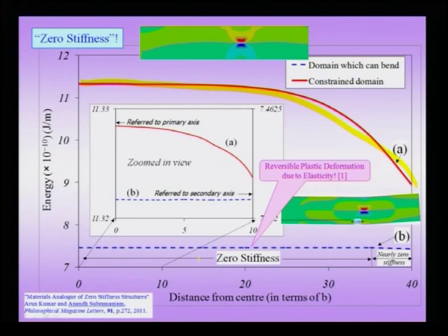Now, if you talk about a dislocation in a thin cylinder like this, and I am positioning my dislocation for instance here, then I move it to a next position here, then here, and in the center of the domain, and I track the energy of the crystal, then it is seen that the energy practically does not change.